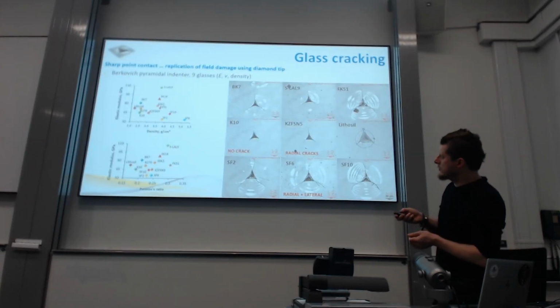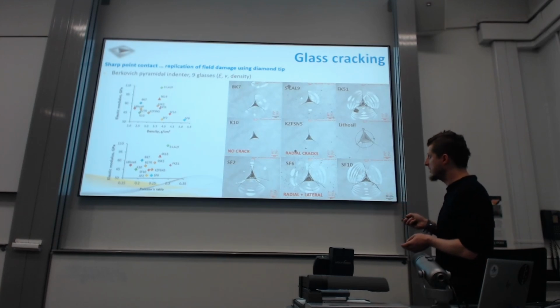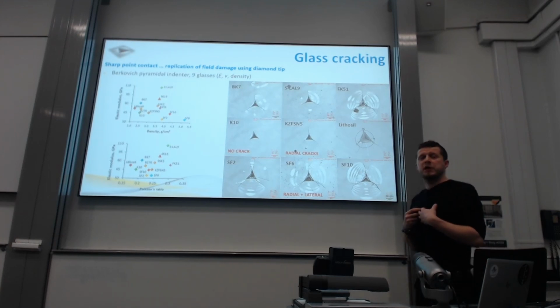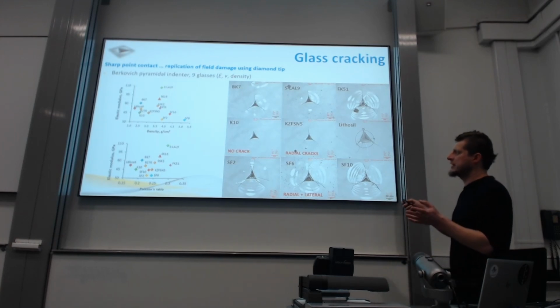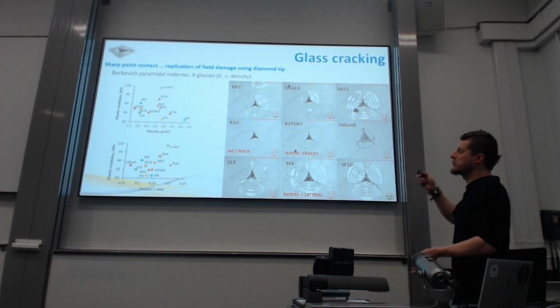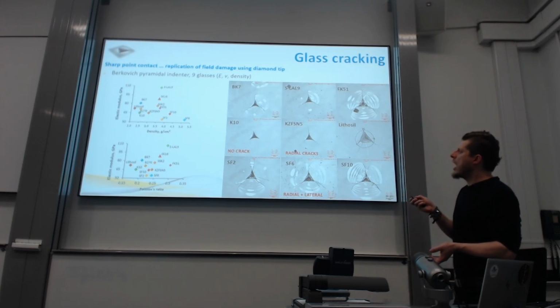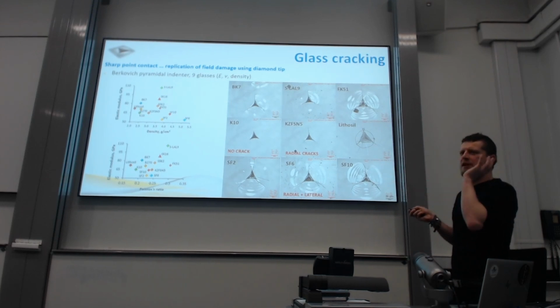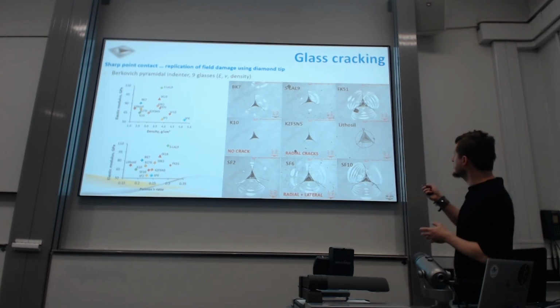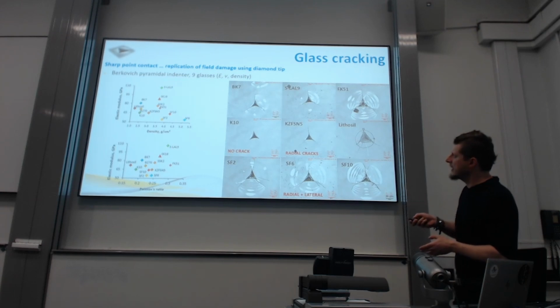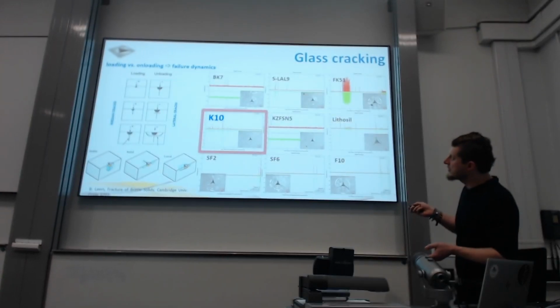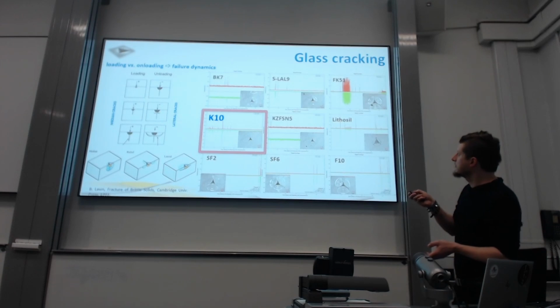What we did was to use several more glasses, because our department is a department of optics. We generally create optical instruments, telescopes. So we just wanted to test how brittle they are and how they can crack, because these telescopes are out in the open. So this is what happened: several different types of cracking of several different glasses, and acoustic emission. So you can see there are a lot of differences.